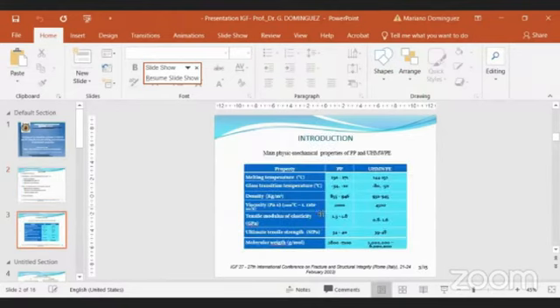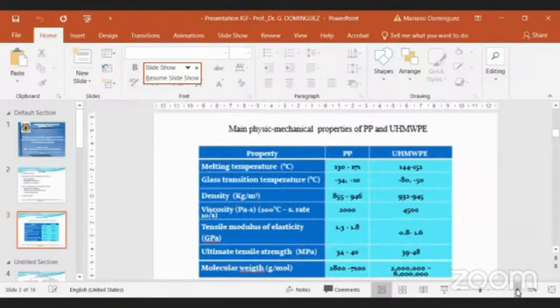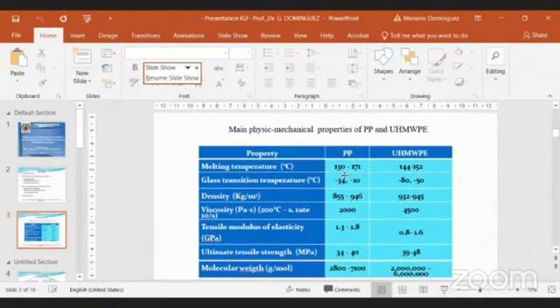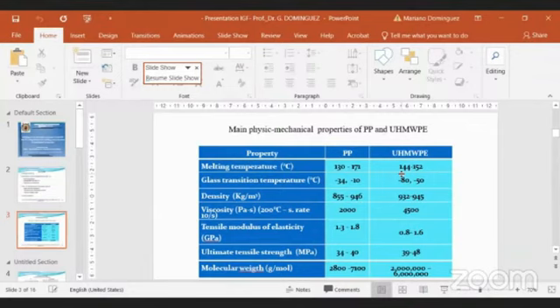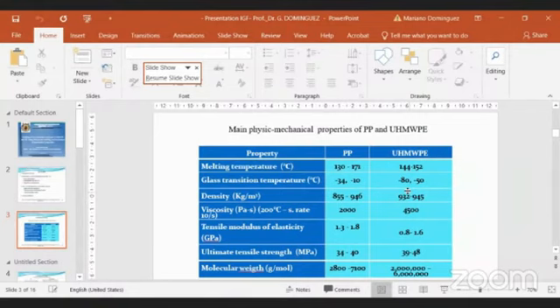Now the introduction. Some main mechanical and physical properties of these two thermoplastics: melting temperatures. For polypropylene it's about 130 to 171. For ultra-high molecular weight it's 144 to 152. The glass transition temperature is very low for both thermoplastics: minus 34, minus 10, minus 80, minus 50. The density is quite similar, typical for thermoplastic materials.